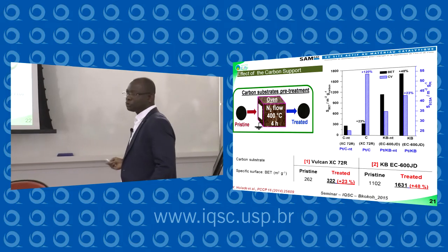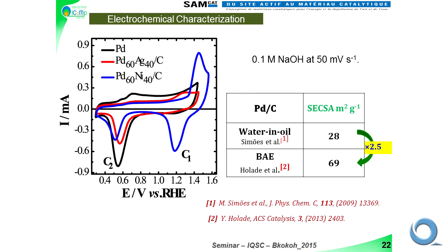The difference is the surface area. Here he multiplied the surface area by 2.5 when he used a method without surfactant. This means that when you finish with water-in-oil, you have some surfactant molecules at the surface which adsorb at the surface of your catalyst. Okay. And he prepared, for example, CO stripping, and this is very well known. With palladium, you have your system with a CO stripping, CO oxidation. And when you use a co-catalyst, you shift the oxidation of CO to a lower potential.